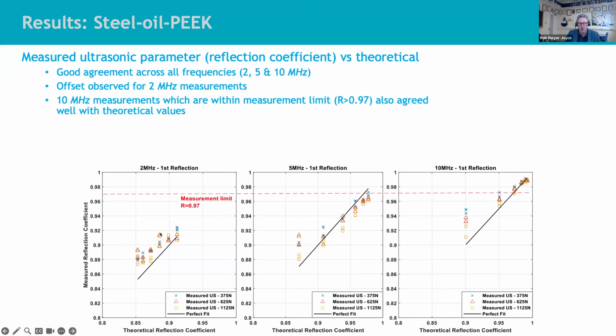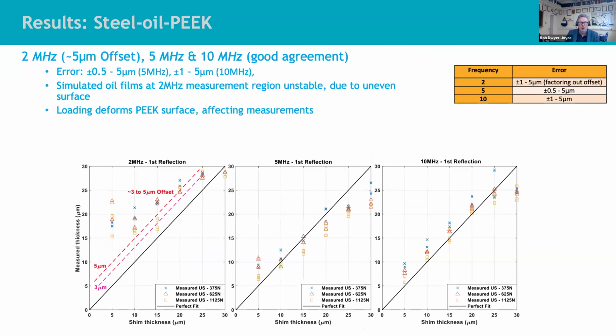Here are our reflection coefficient measurements for a 2 megahertz, a 5 megahertz, and a 10 megahertz sensor. But we tend to get an offset in the 2 megahertz region. I'll show you something in a minute about possibly why that's the case. When we convert that to oil film thickness, it's not quite as clean as steel, oil, steel, but you can still get measurements in the right sort of region.